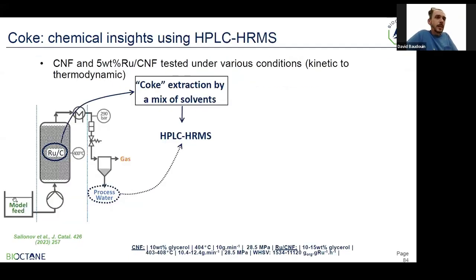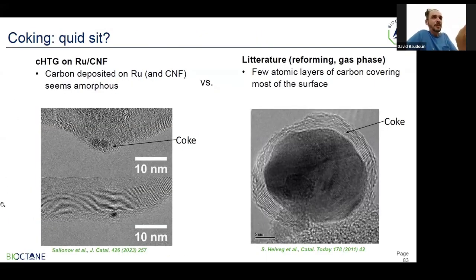Now, in supercritical water conditions, if you come back to the former slides, on the left, the deposition that we observed was very different. It seems to be much more homogeneous and much more amorphous. We never observed the formation of this type of layers that you see on the right. Next slide, please.